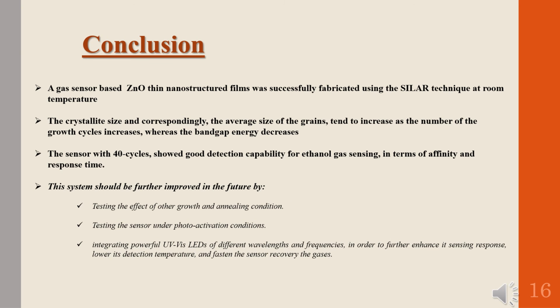As a conclusion, we have successfully fabricated a gas sensor using the SILAR technique. Then we have explored the sensor properties under different growth conditions, also the evolution of the grain size as a function of the number of cycles. Finally, we found that the sensor with 40 cycles showed good detection capability for ethanol gas sensing in terms of affinity and response time. For perspectives, the system should be further improved by testing the effect of other growth and annealing conditions, testing the sensor under photoactivation conditions, and integrating powerful UV LEDs for different wavelengths and frequencies.